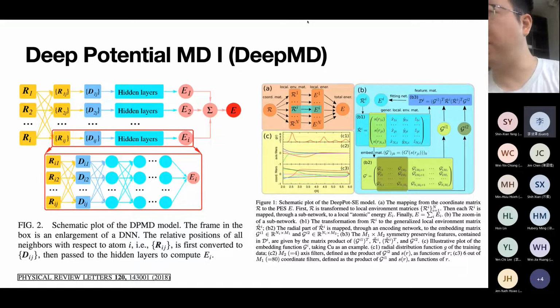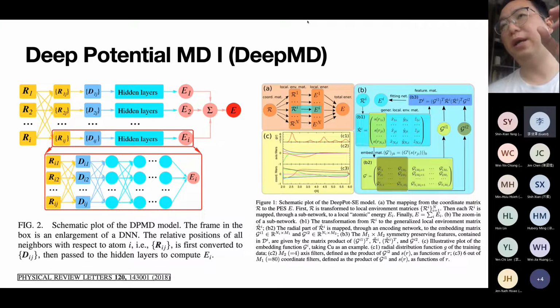So if you look at C1, you can see that there are some peaks at some fixed positions. That sort of corresponds to the atomic positions, the radial distribution of the atoms in the cluster that's centered at i. So you can think of it as at maybe 2.5 angstroms there's a shell of atoms, and then at 4.5 angstroms there's another shell of atoms, and for the smaller peaks at 3.5 angstroms and maybe at 5.25 angstroms and at 5.75 angstroms there's a smaller shell of atoms. So that's basically some physically intuitive idea of what G does. G sort of captures the distribution of the atoms in the cluster around its center. Okay.